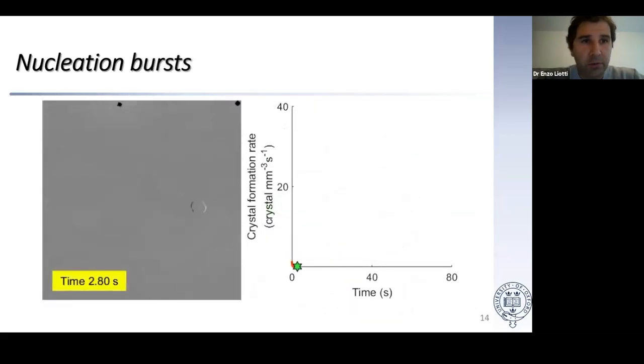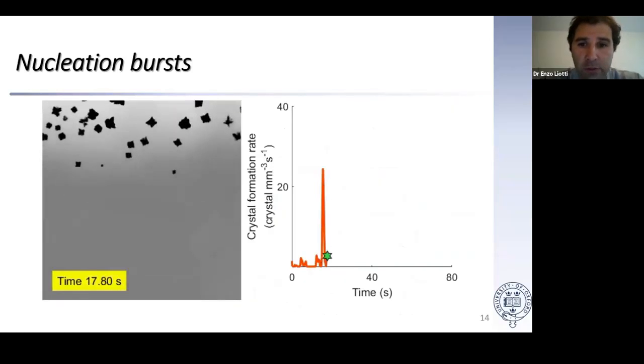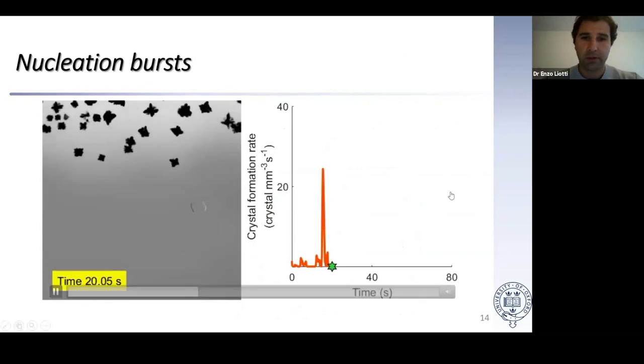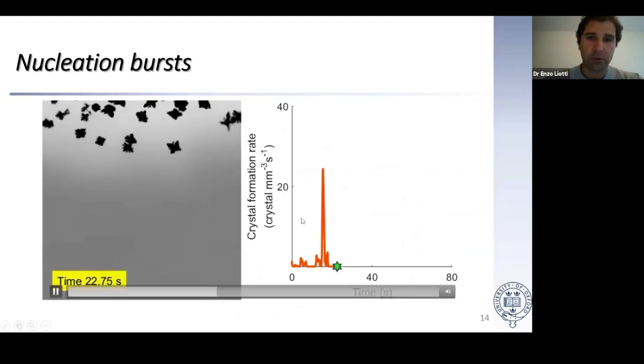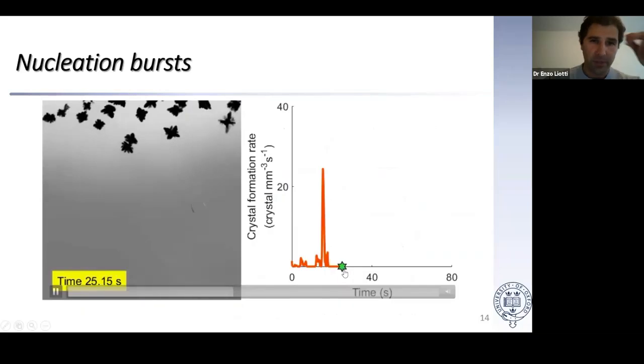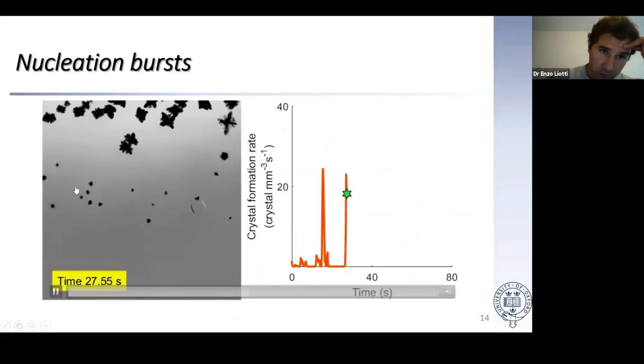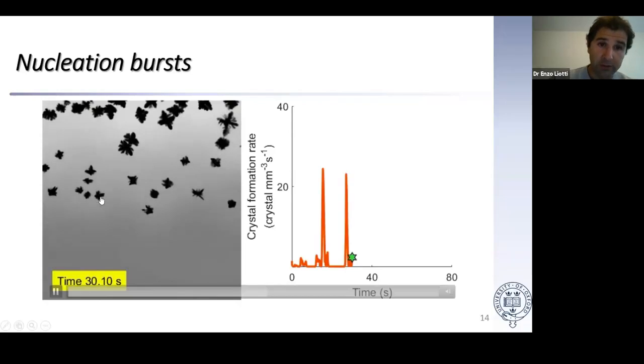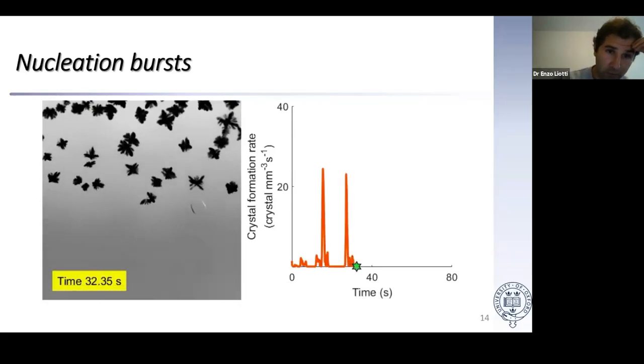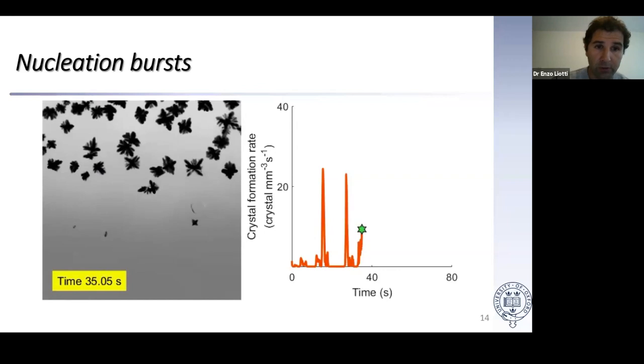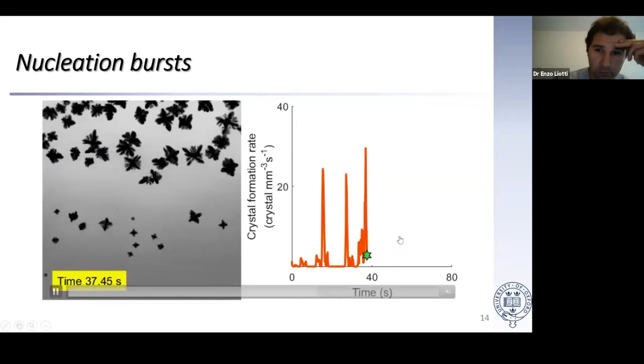Finally, another insight we found is that by analyzing the crystal formation rate, we confirmed that nucleation happens in bursts and is not a continuous phenomenon. This again has been predicted in theory, but these data are the first experimental evidence. As you see here in the graph, it is plotting the real-time crystal formation. There was a first wave, and then there will be a second wave in a minute, in which the crystals form all in bursts essentially, right? They don't actually form continually. So now there is a moment in which there is low nucleation, and then there is a third burst.